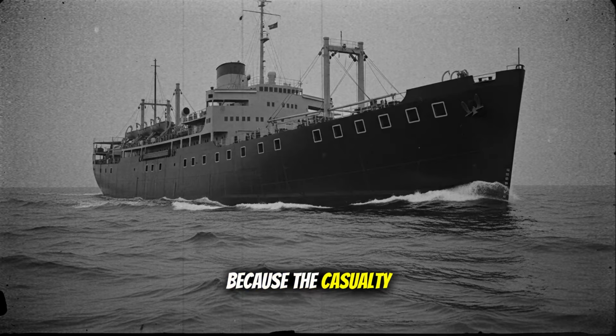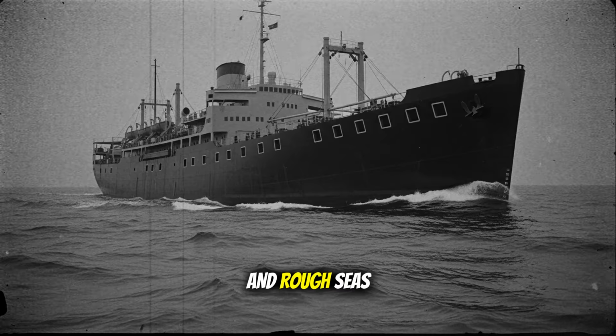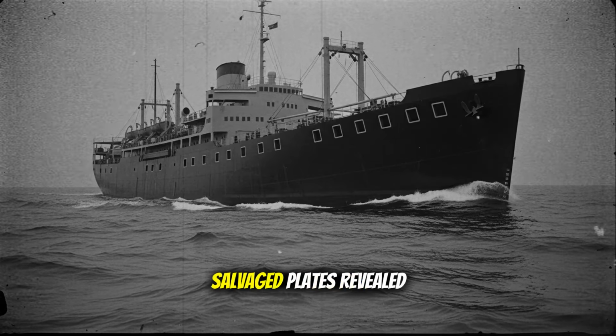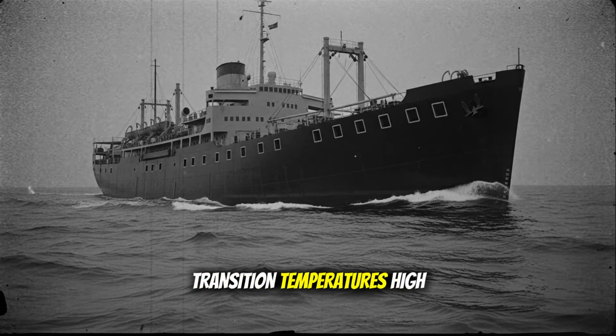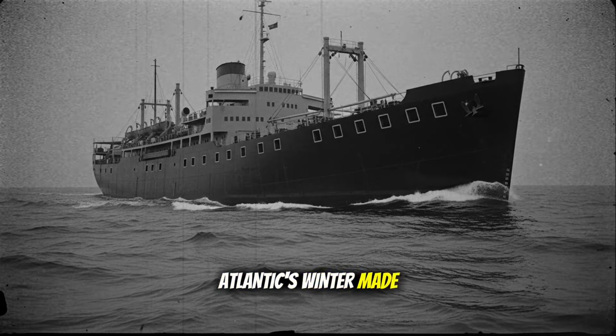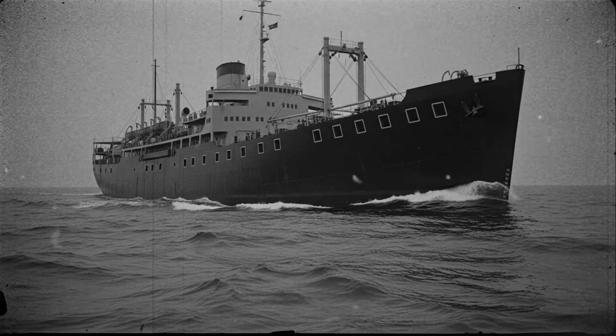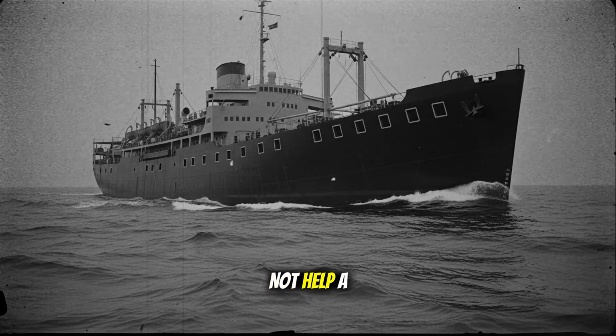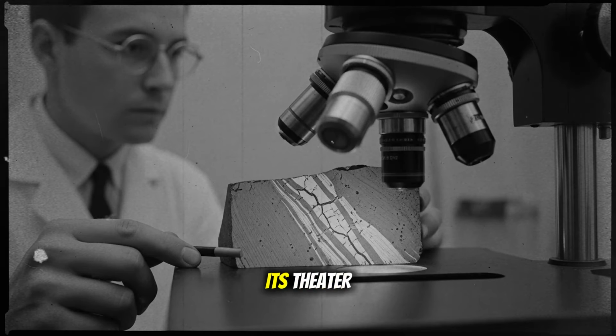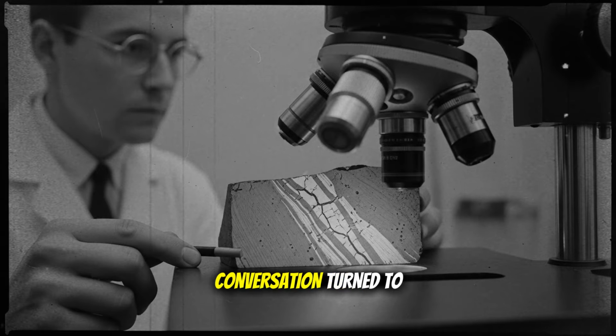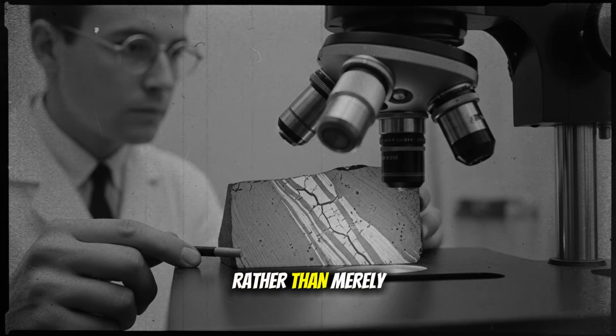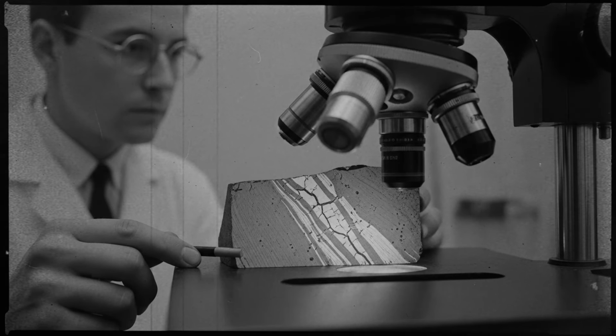But the broader pattern refused to be explained away by workmanship alone, because the casualty rate spiked in cold weather and rough seas, and tests on salvaged plates revealed transition temperatures high enough that the North Atlantic's winter made them notch brittle by default. Blaming hands could not help a hull that had the wrong toughness for its theater, and so the conversation turned to properties and shapes rather than merely to speed and supervision.